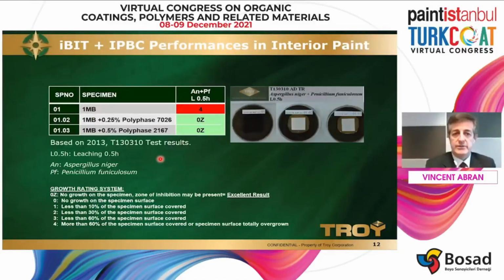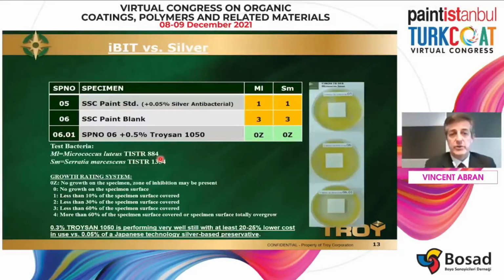Now, if we look at the next test, here we compare a paint which is using silver antibacterial performance. This is not our product. And then we compare with immobilized BIT here in the same paint. So this paint here, of course, it's sensitive to bacteria, as you can see. So here we are testing against Micrococcus luteus and Serratia marcescens. So two types of bacteria, different tests, different bacteria, but similar performance claim, antibacterial. So the paint blank without protection is very sensitive to bacteria. The bacteria are growing onto the surface of the specimen.